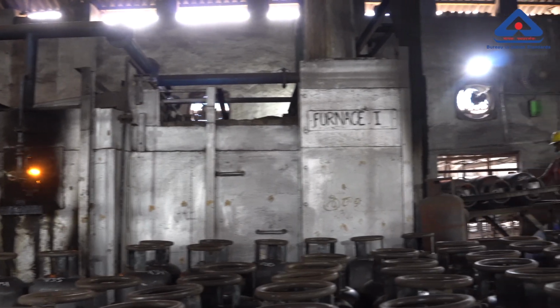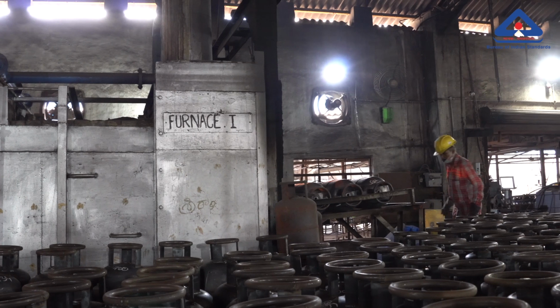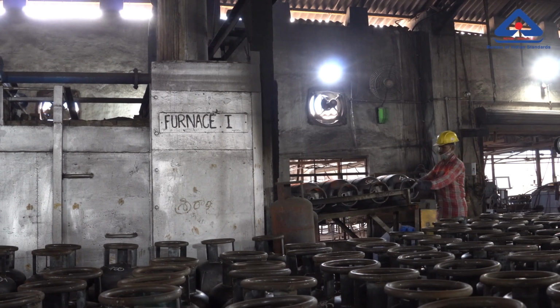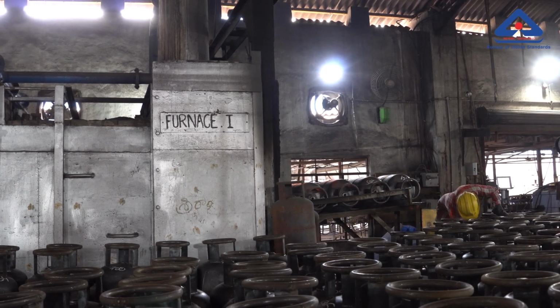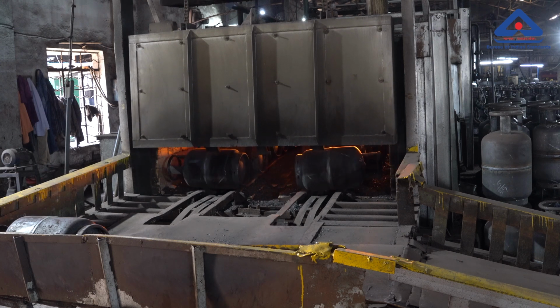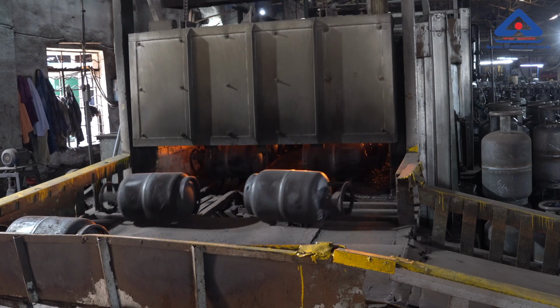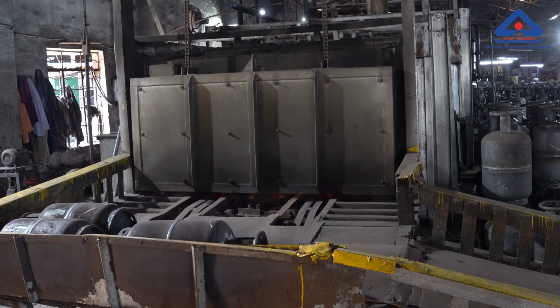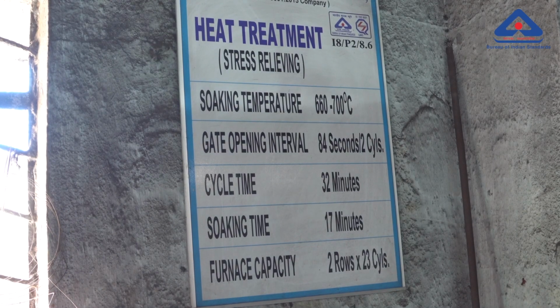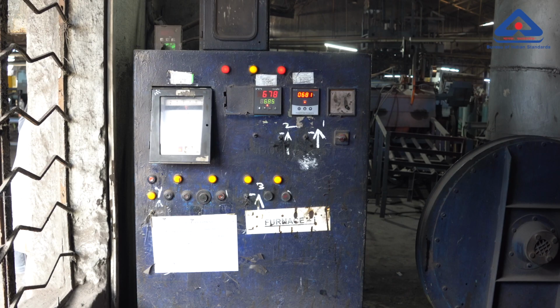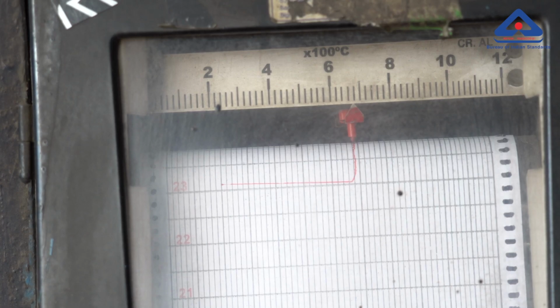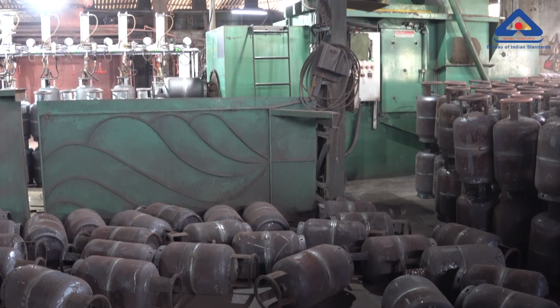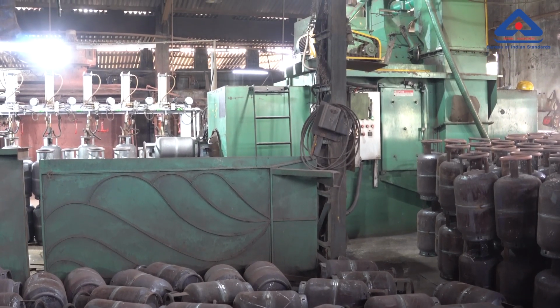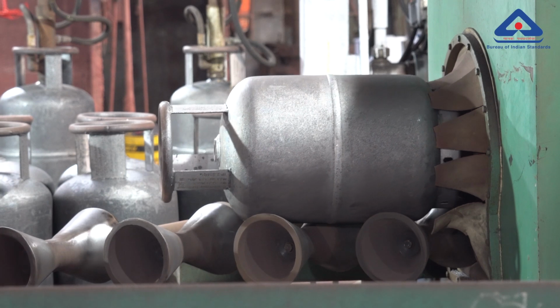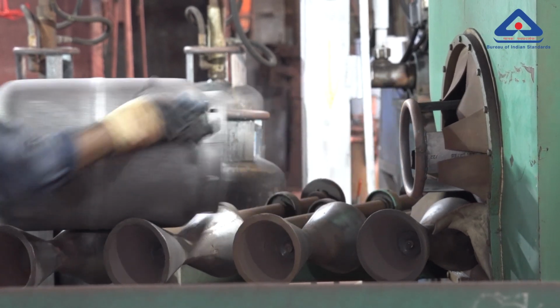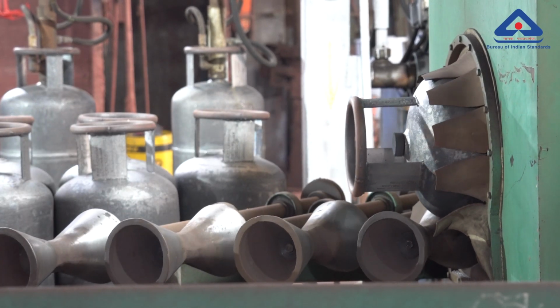The cylinders are serially loaded batch-wise into a furnace to relieve the stresses which are developed during cold working and welding. The temperature is maintained at 660 to 700 degrees Celsius. This process is called heat treatment. This is another critical process which provides the required mechanical strength to the cylinders. After cooling, these cylinders are sent through a grit blasting cabinet to remove external scale, soot, dirt, etc. from the entire surface of the cylinder.